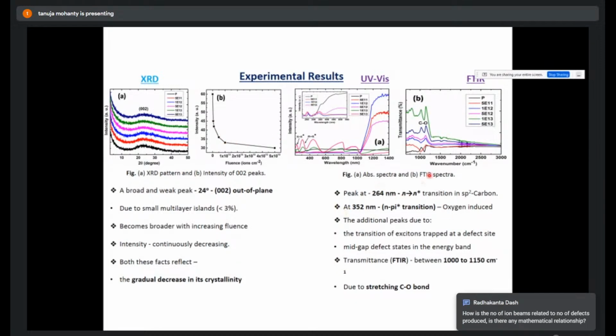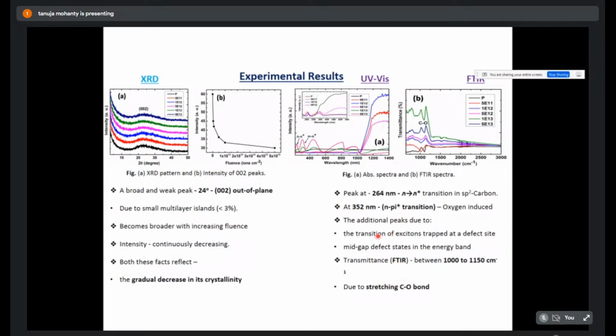And here we also have the UV-visible optical transitions, because as I said, these are optoelectronic studies. So we have done this UV-visible absorption as well as the FTIR. The FTIR band around 1000 says about the C-O, carbon-oxygen stretching bond effect, and the peak at 264 nanometer says the pi-to-pi star transition.